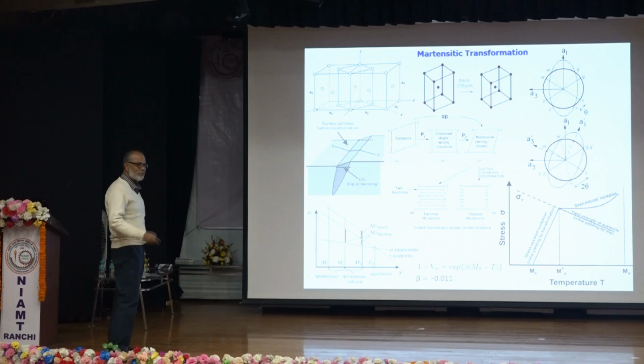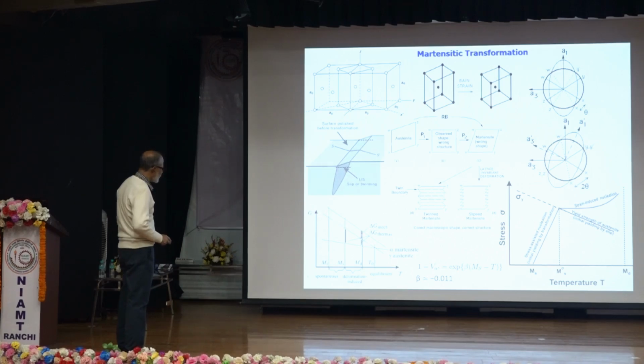Now regarding driving force, as I have mentioned, it is not chemically driven. It is not thermal driven. So this is the austenite free energy line, and it is the martensite free energy line. We know, perhaps it is taught in mechanical engineering also, when they intersect, it is the equilibrium. We call it T0, right? So below the equilibrium temperature, there is a temperature Ms where we achieve some thermal energy, which transforms austenite to martensite. So we require cooling below the equilibrium temperature to a certain lower level, below which martensitic transformation will take place. You may call it thermal driving force, or you may call it chemical driving force.